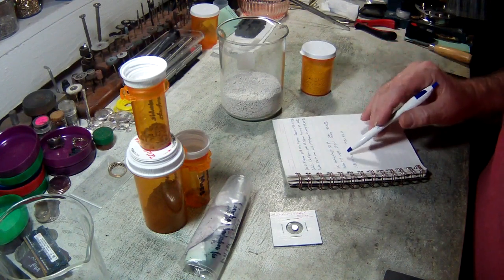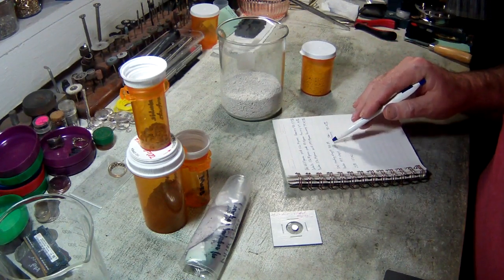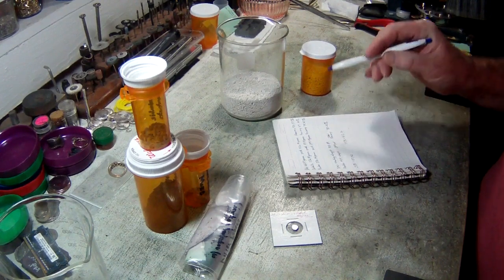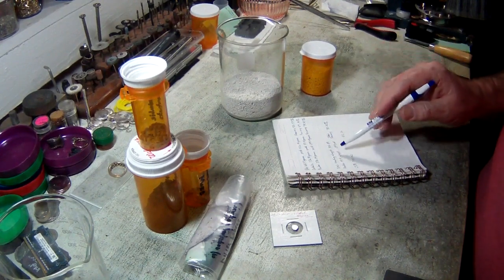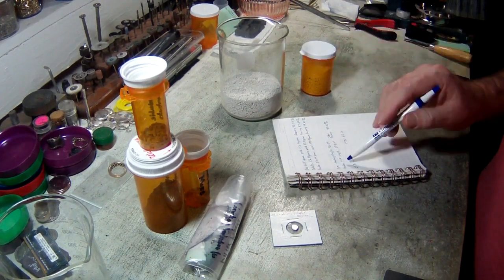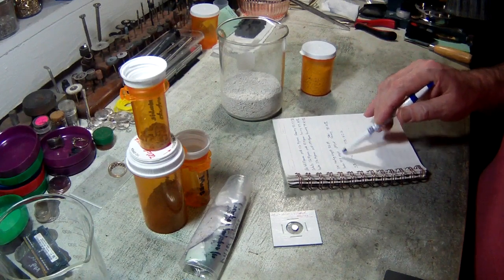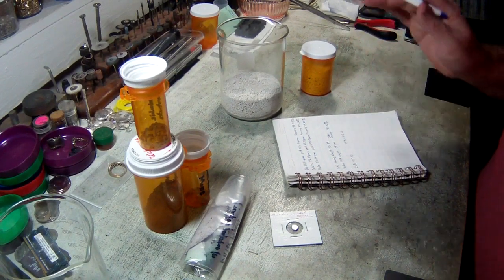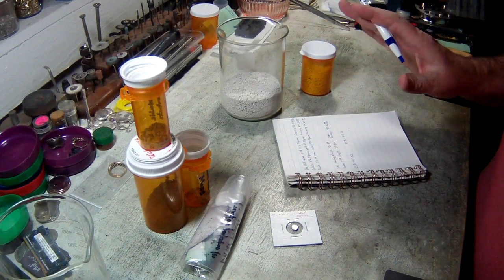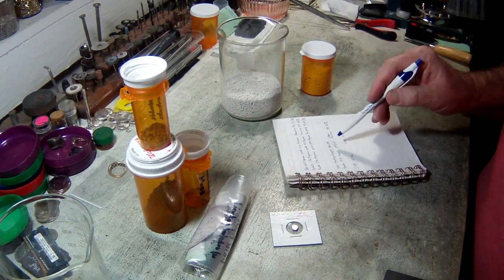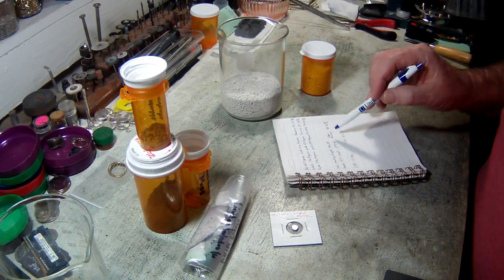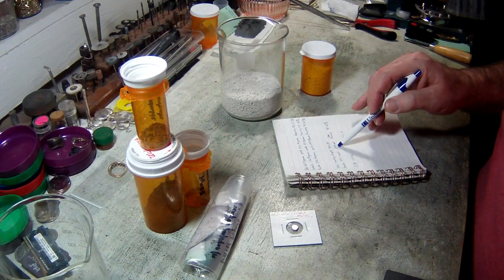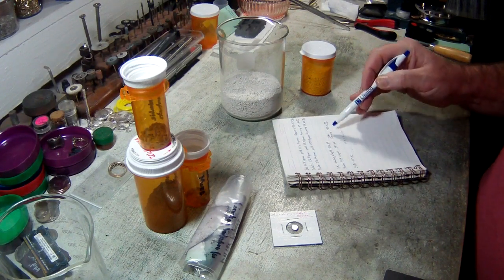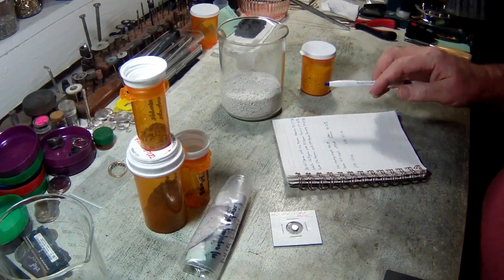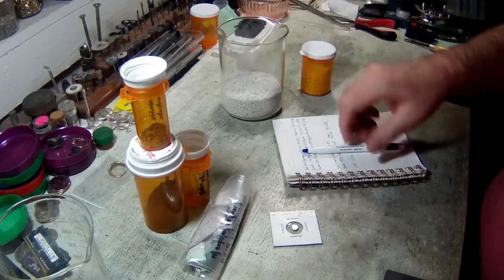So in the long run, we started with a total weight of 702.89 grams of material. We ended up with our powders, which are 99.9% pure, thereabouts. I mean, it's maybe actually a little purer than that probably, for a total weight of 549.68 grams, which was a total of 78.20% recovery.